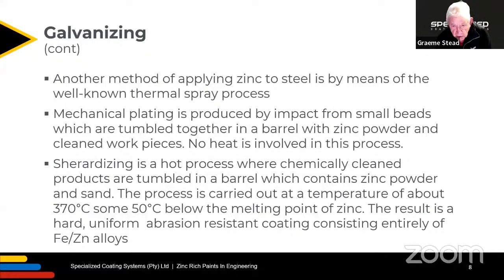And sherardizing is a hot process where chemically clean products are tumbled in a barrel which contains zinc powder and sand. The process is carried out at a temperature of about 370 degrees Celsius, some 50 Celsius below the melting point of zinc. The result is a hard, uniform, abrasion-resistant coating consisting entirely of iron zinc alloys. And this is very effective for fasteners, which are generally not galvanized because of hydrogen embrittlement and the danger of progressive cracking.